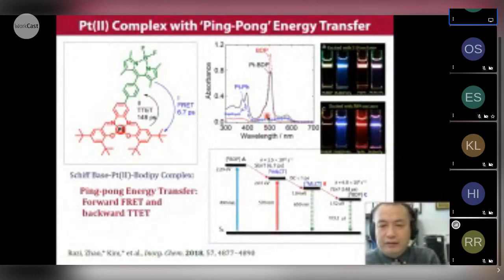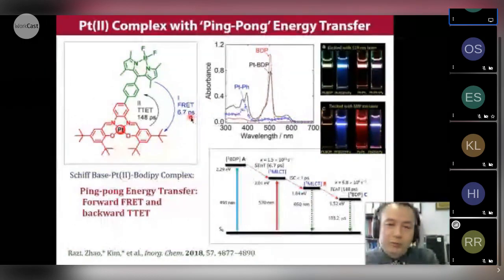The last example is we prepared a complex with Ping-Pong energy transfer. That means we can selectively excite the green part. The green part is actually isolated from the red one because we use the phenyl linker between these two parts. So actually they take perpendicular geometry. So there is no pi conjugation between these two parts. So we can treat these two parts as separated ones. The singlet energy transfer takes about 7 picoseconds.